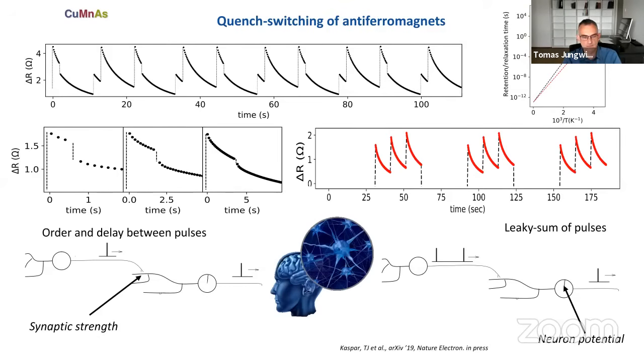I've already mentioned the metastability of the retention, if you want, or of the stored information in these devices. So indeed, if we switch the device by a short pulse, which can be as short as a femtosecond laser pulse, or it can be a microsecond or millisecond pulse, and then follow the readout signal, we see that there is this smooth relaxation of the signal. Now, the typical retention or relaxation time that we observe is exponentially dependent on temperature. So our signal that we see here would relax on time scales of seconds or tens of seconds at room temperature. If we cool the system down to 200 Kelvin, it becomes a time scale of years.